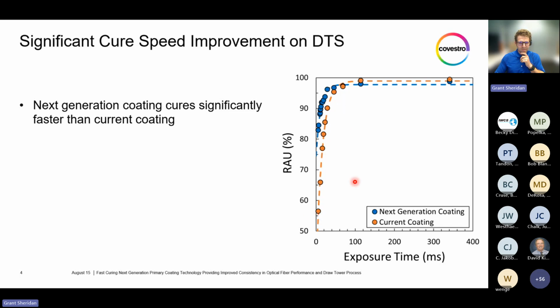As we can see down here at the very short exposure time, this next generation coating has already achieved 80%, 82% cure at just 5 millisecond exposure time, while the current coating technology is lagging all the way down at 55% cure, which would pose challenges as draw speeds are increased over 3,000 meters per minute, and exposure times are significantly reduced. Now, we did fit this data to a pseudo first order kinetic model to try and be more quantitative in our analysis between this next generation coating and the current coating.